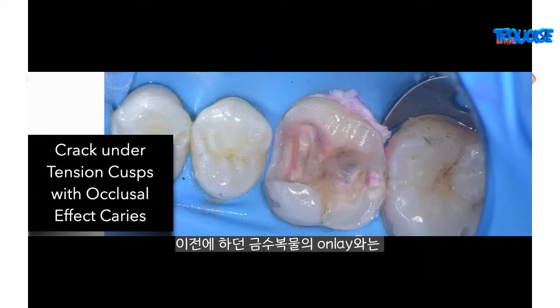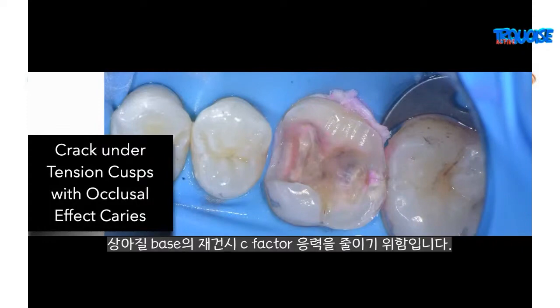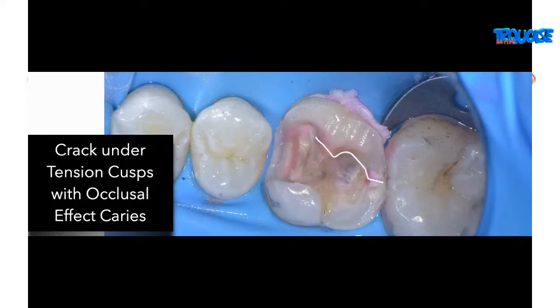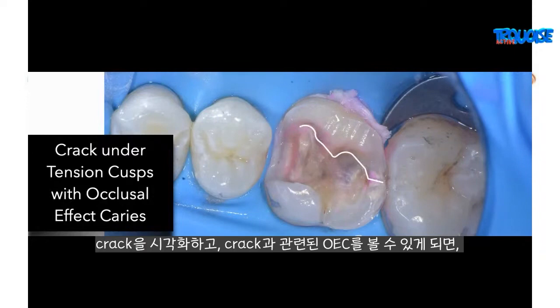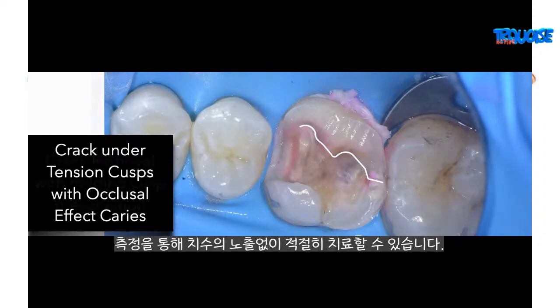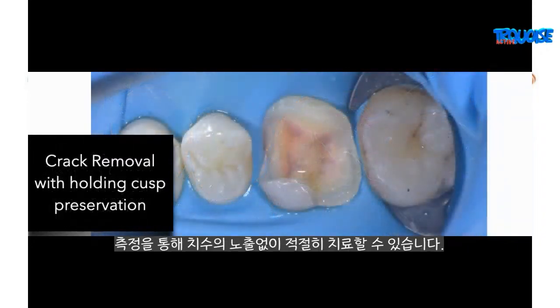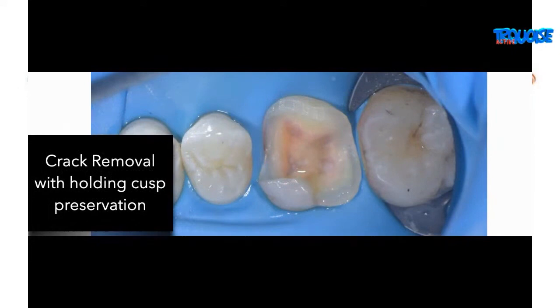mechanical strengthening. So we're not onlaying cusps for the same reasons as we used to onlay cusps for a gold restoration, for example, an onlay restoration. This is actually for visualization and to decrease C-factor stresses in the reconstruction of the dentin base. Visualizing the cracks, we see the occlusal effect caries associated with the cracks, and then we can appropriately treat that without exposing the pulp by using our measurements.